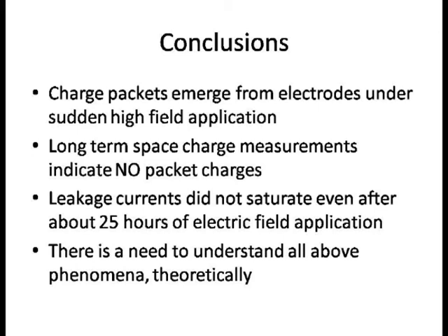I have not told this in the presentation, but short period, very sudden application of voltage is leading to charge pulses, charge packets emerging from the electrodes. But when you conduct the experiment for 5 hours, the 30 hours experiment, we did not observe that. Only for a few minutes the charge accumulation took place, and after that it stabilized and there was no problem.